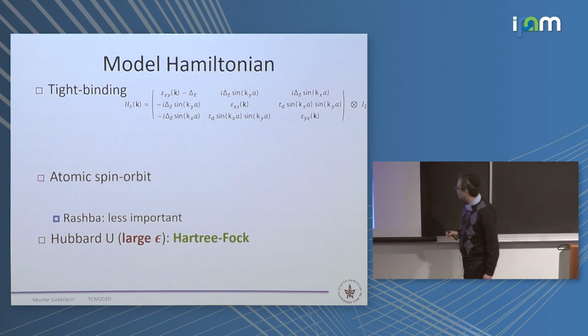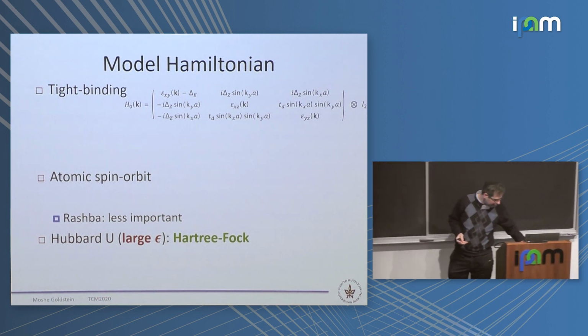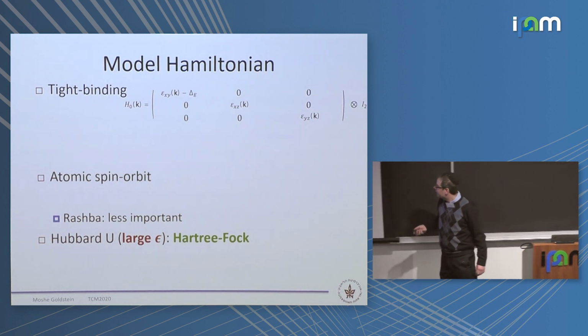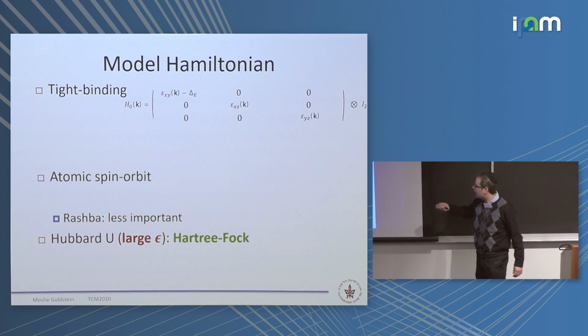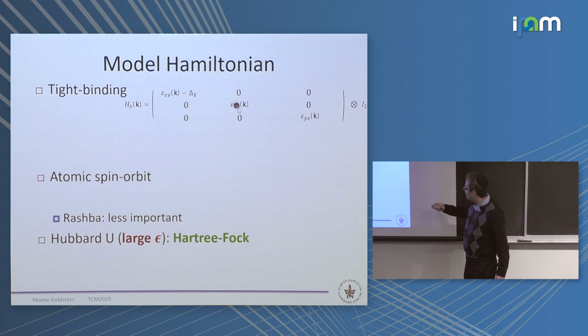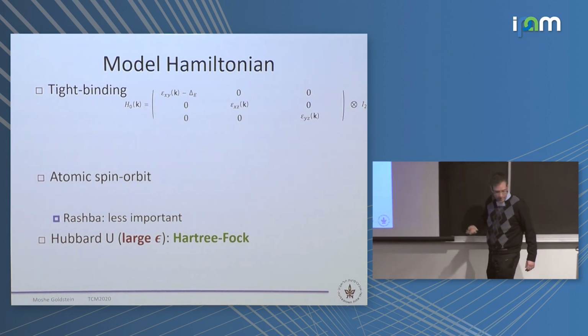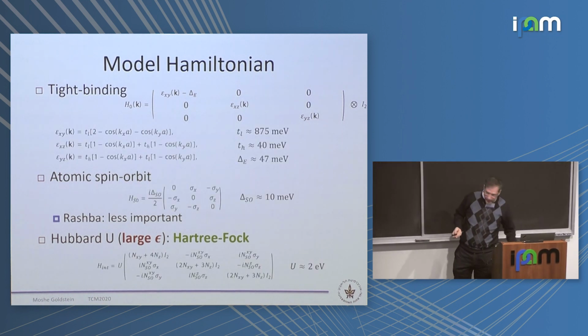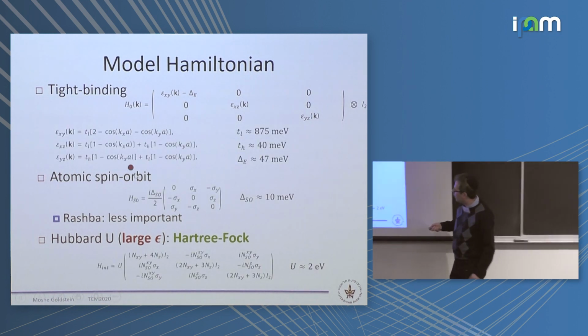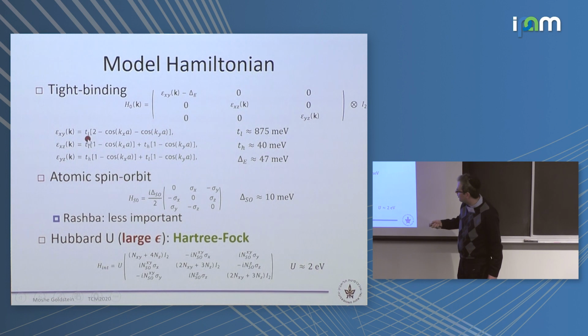So there is the tight binding part. It has many terms, but most of them are not actually important for the physics. The main thing is this diagonal part. So the basis is xy, xz, yz cross spin up and down. There is the part which is spin independent, and it encodes the different mass or the different hopping element along different directions. So there is a large and a small one, and there is a factor of 20 almost between them. And also there is this delta E.